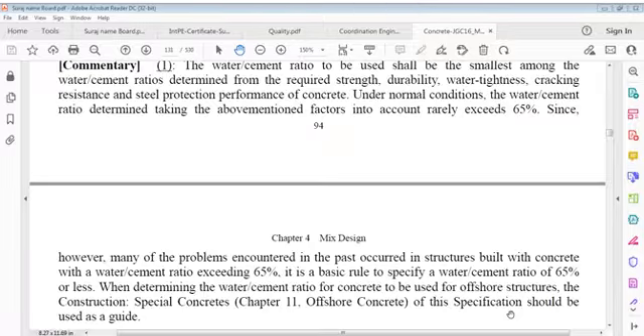Under normal conditions, the water cement ratio determined taking these factors into account rarely exceeds 65%, that is 0.65. However, many of the problems encountered in the past occurred in structures built with concrete with a water cement ratio exceeding 65%. It is a basic rule to specify a water cement ratio of 65% or less when determining water cement ratio for concrete to be used for offshore structures. Offshore is special concrete construction.